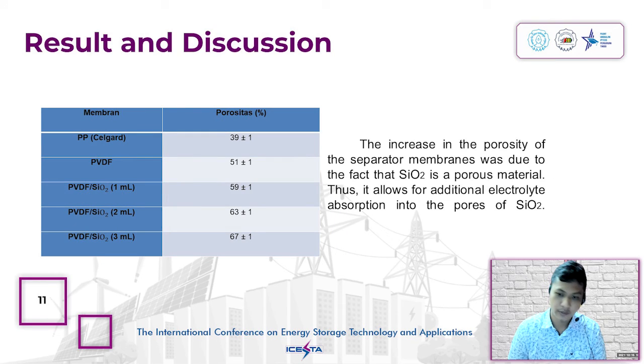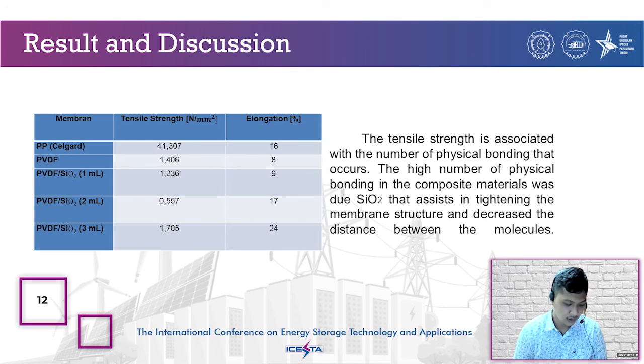Next is porosity of the membrane. The increase in the porosity of the separator membrane was due to the fact that SiO2 is a porous material. Thus, it allows for additional electrolyte absorption into the pores of SiO2. Next is mechanical strength. The tensile strength is associated with the number of physical bonds that occur. The high number of physical bonds in the composite material was due to SiO2, which assists in tightening the membrane structure and decreases the distance between the molecules.